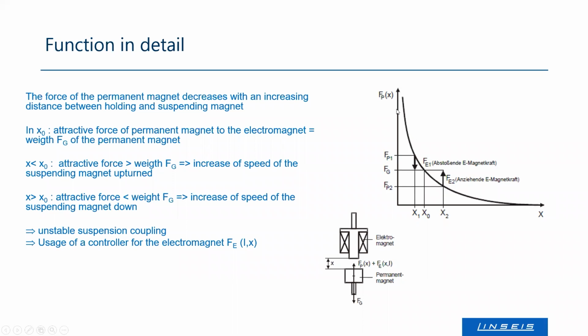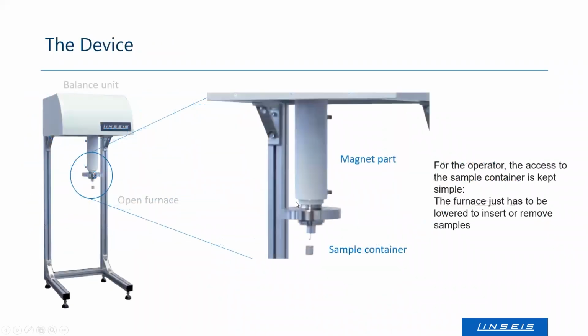If the force gets too weak, however, the elevated part in your balance will just fall down, and therefore you have to increase the voltage of the electric magnet. And that's why you have to precisely control the force by PID so that the coupling is kept constant. The whole regulation circle and the whole setup will cause a little bit of noise on the signal, and that's also the reason why the resolution of a magnetic suspension balance is a little bit worse than that of a classical thermobalance. However, you gain the advantage that you can use corrosive atmospheres in an encapsulated chamber. And that's why it's very important to have a good magnetic coupling.